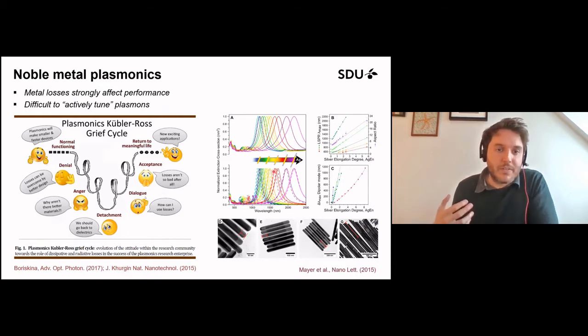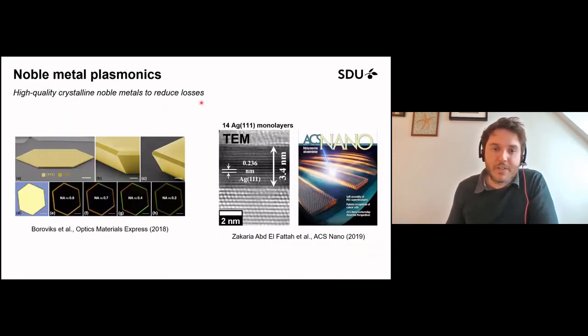Now, in noble metal plasmonics, there's a recent trend that actually is being explored at SDU, in the Center for Nano-Optics, to go to new types of noble metals. So they do have these losses, but you can make them better, essentially. If you can make them completely crystalline, you already win just by having a more ordered system. It can be atomically flat, so you start to sort of iron out the wrinkles, and ultimately you can have a higher quality plasmonic resonator.